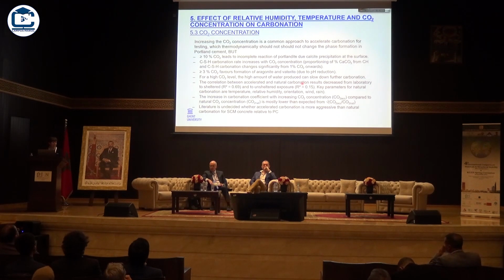Carbon dioxide concentration is often increased in accelerated tests, but is this a good way to study carbonation? That's always the question. And actually in standards, previously also in our lab, we tested at 10% carbon dioxide, but it is often mentioned that you really change the mechanisms in that way, and that this is not a good way to accelerate carbonation, so you should remain below a certain level of carbon dioxide if you do not want to change the mechanism. Because indeed other things may happen at increased carbon dioxide concentration. For instance, more calcite precipitation on the surface of the portlandite.